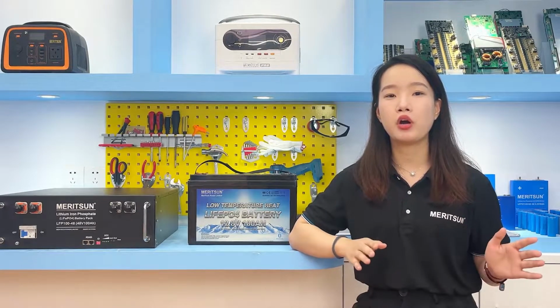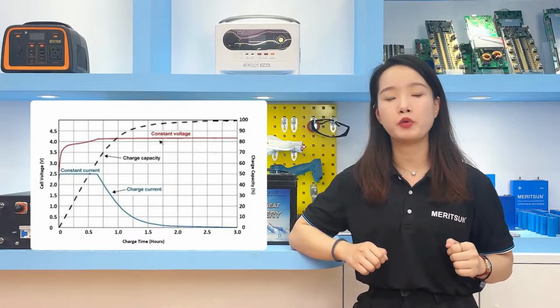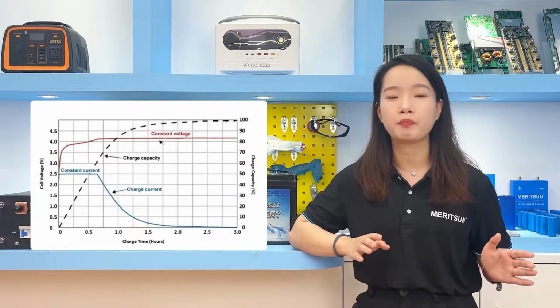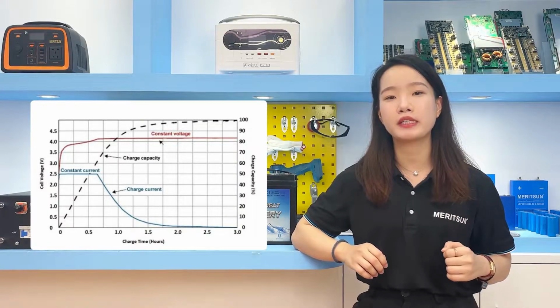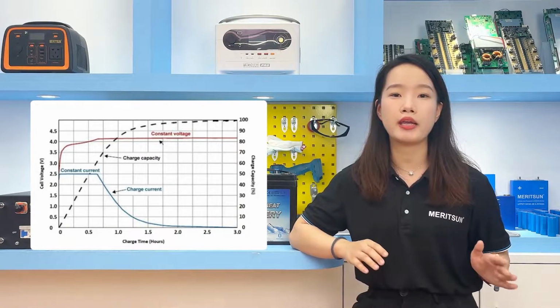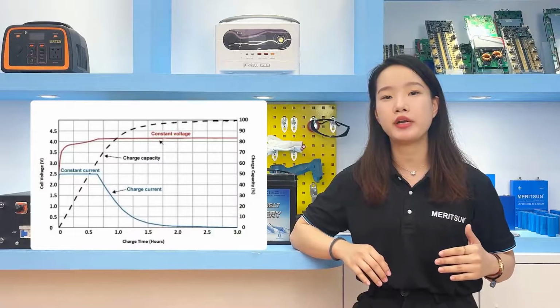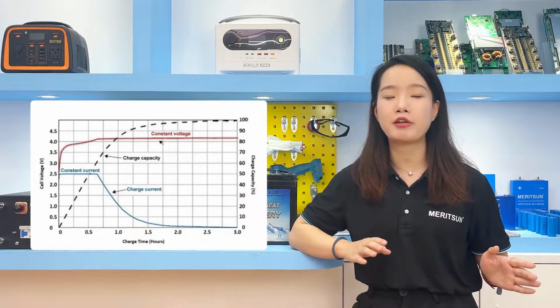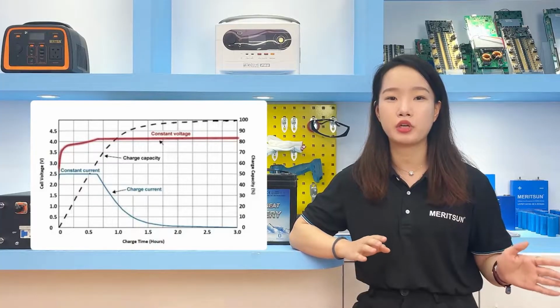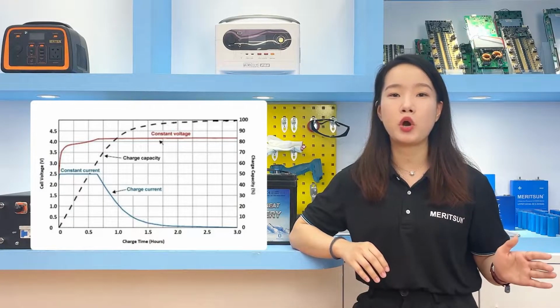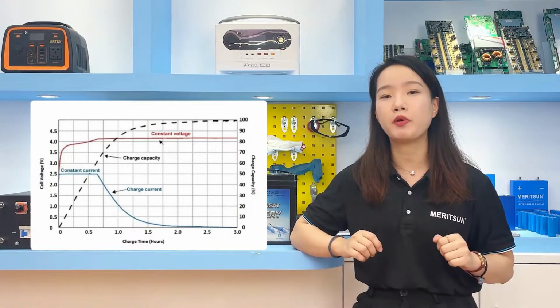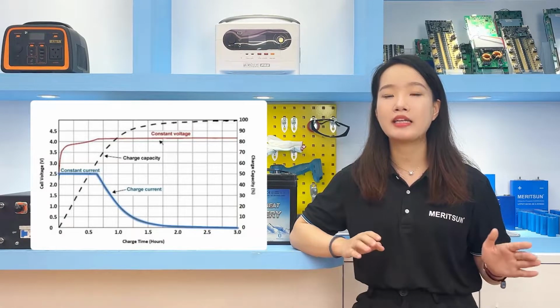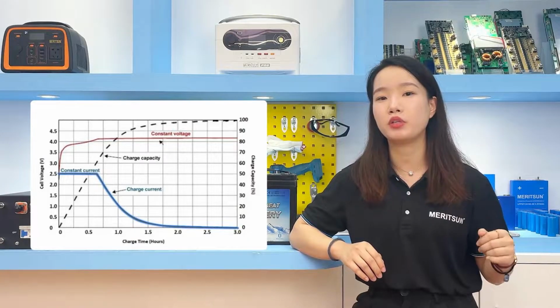Lithium iron phosphate battery charging is divided into two stages. The first is constant current charge, until reaching the terminal voltage, and then it changes to constant voltage charge. For example, a 3.2 volt 100 ampere-hour battery cell has a terminal charge voltage of 3.65 volt. The battery cell is charged at a constant current of 50 ampere. The charge rate is 0.5C. At the beginning, the battery cell voltage increases with the large load. And when the voltage is close to 3.65 volt, it changes to 3.65 volt constant voltage charge, and the current gradually drops with the voltage in little change.